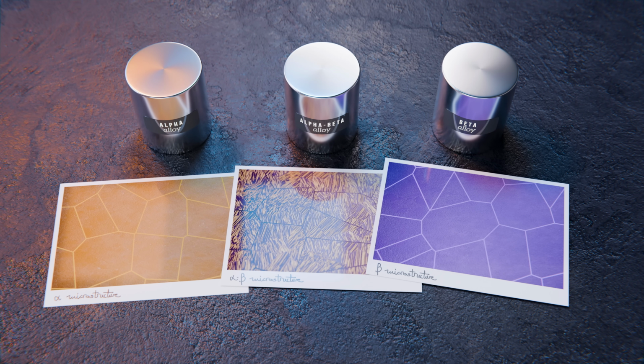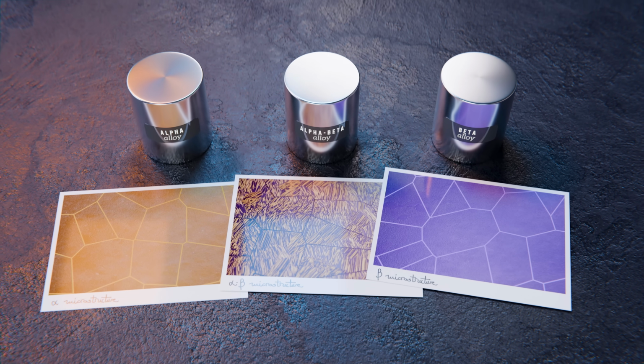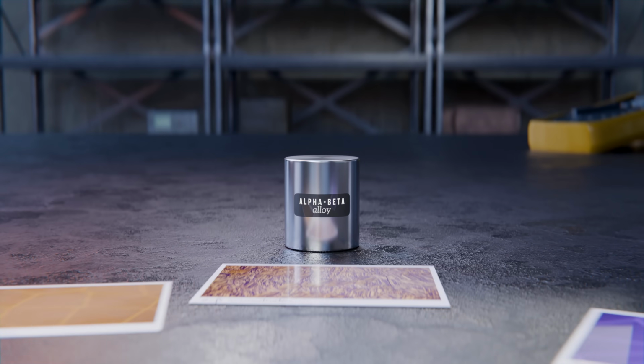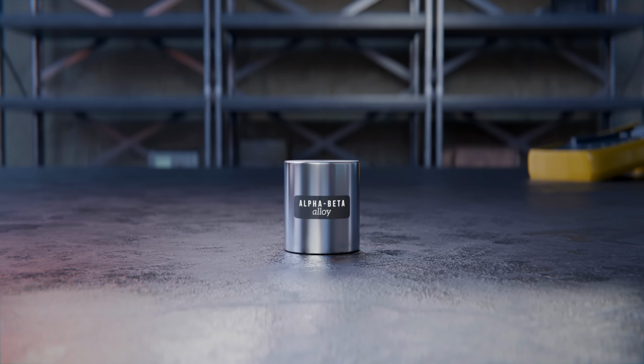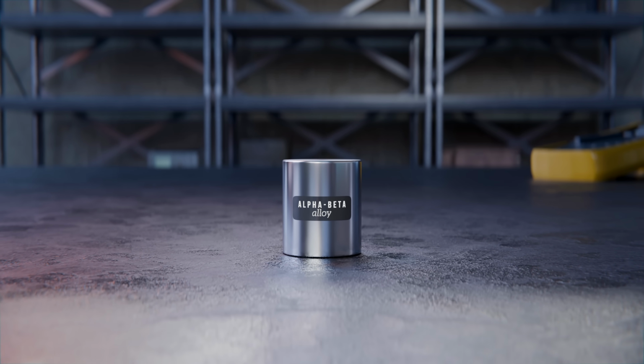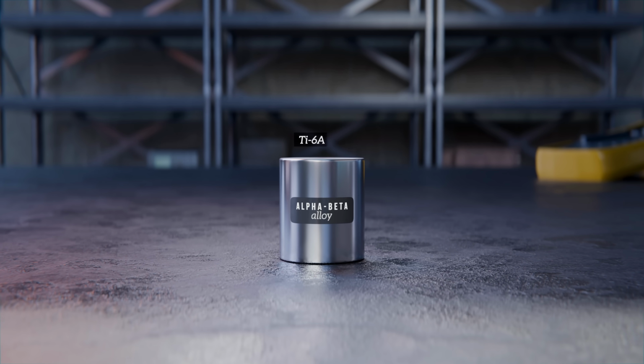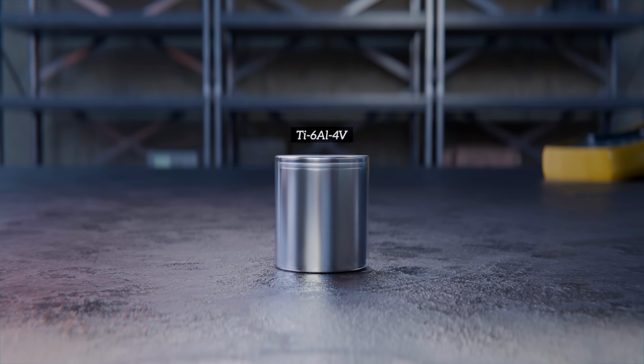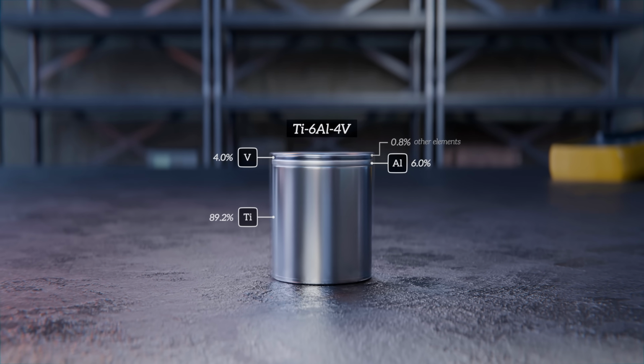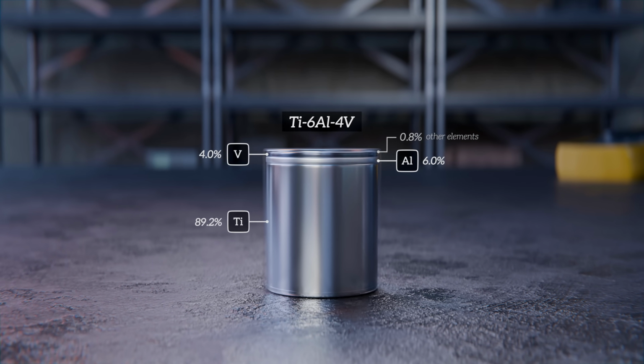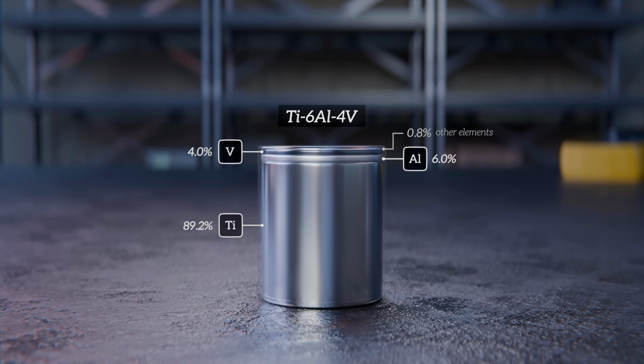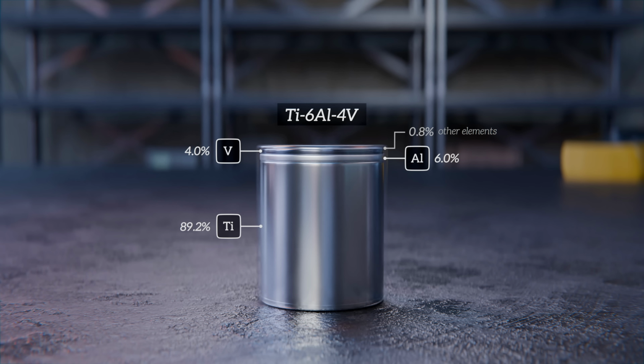Alpha-beta alloys offer a good balance of properties, combining the strength and creep resistance of the alpha phase with the ductility of the beta phase. It's no surprise then that the most widely used titanium alloy falls into this category. Ti-64 contains 6% aluminum, an alpha stabilizer, and 4% vanadium, a beta stabilizer. It accounts for more than half of all commercially used titanium, and is often used in demanding applications, including the fan hub that failed on Air France Flight 66.